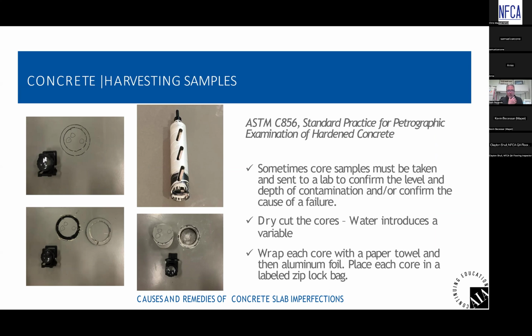Okay, this is a project that had some small blisters in it, and we wanted to send core samples to a third-party lab so that they could evaluate it. And the whole idea is we wanted to give them a totally intact system so that they can peel back the onion, basically, and then evaluate and conduct a petrographic analysis to confirm the cause of the condition. So you can see in the first picture, top left, that I drew circles on where the blisters were for identification reasons. So the lab knows exactly where the blister was.